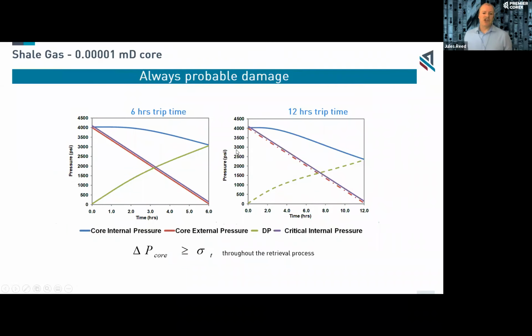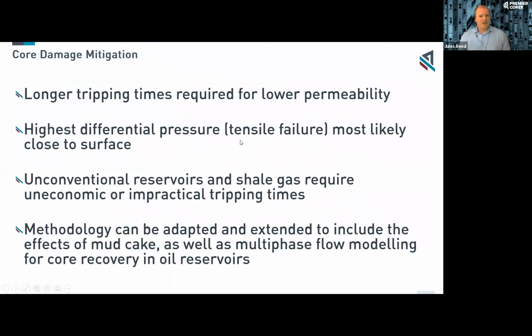If you model this for shale, and this was done in the paper, what you find is you can never keep the differential pressure below that critical strength line. So in shale, you're always going to fracture the core. So what you generally need is longer tripping times for lower permeability. As you get closer to the surface, you need to slow down, and the differential pressure, the gas begins to expand exponentially.